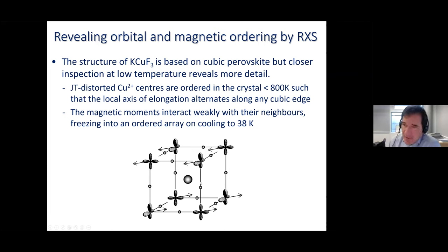So in this structure, the fact that this particular atomic level in copper is only partly occupied means that the copper atom, which ought to be coordinated by a perfect octahedral arrangement of fluorine, is now distorted so that this fluorine is further away than this one, for example. So we end up with a structural distortion as a consequence of this incomplete filling of the orbitals.